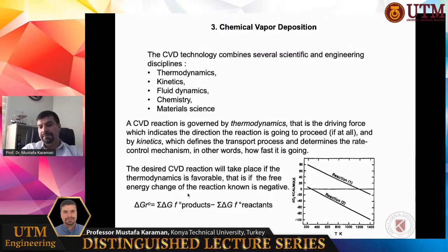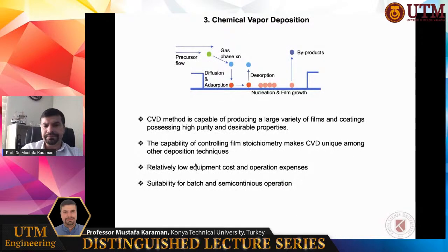Here in this figure, you can see reaction 1 and reaction 2. For example, at 800 degrees Kelvin, reaction 1 will not proceed. It's not thermodynamically feasible because you can see delta G of formation is positive, but reaction 2 is favorable. So you can calculate this from thermodynamics.